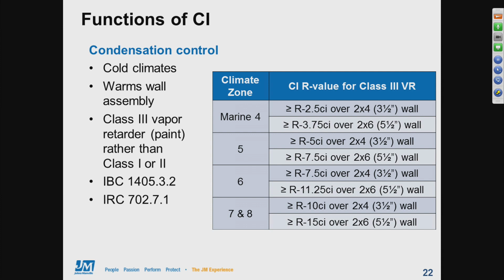So we've talked about how CI can control condensation by reducing thermal bridging in cold spots. And the building code also recognizes that if we add CI, we reduce the condensation risks inside the wall, and so the code will allow a Class 3 vapor retarder, which is typically just latex paint, to be used in many cold climates instead of requiring a Class 1 or 2 vapor retarder, which would typically be polyethylene sheets or kraft-faced cavity insulation. But to qualify, there's a minimum amount of CI required, and that depends on the climate and the thickness of the wall.